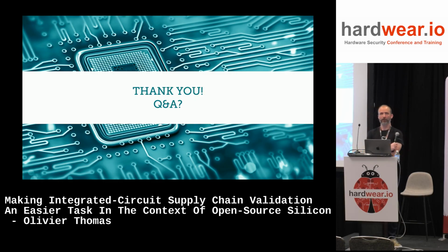So this is taken into account, because dopant modification is something that you can make visible. Pictures are not lying. That's the cool thing about looking at chips. I like when people say we will prevent reverse engineering. I would say good luck, because all of the countermeasures will not work. If you modify the dopant, you have chemicals that will etch specific dopant types, so you make them visible. You make the difference on your pictures.